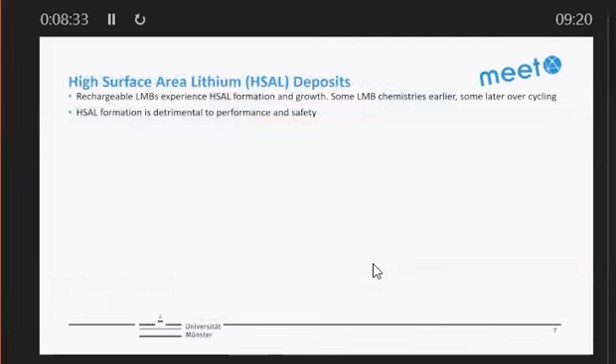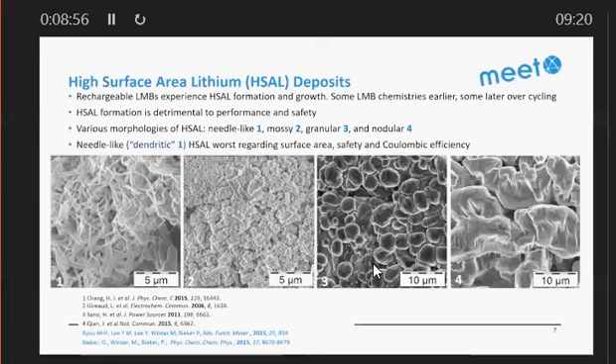Okay, high surface area lithium metal deposits, there are quite a few. And actually, all of the lithium metal batteries, including solid state, fail after some time because lithium metal gets deposited more roughly. Okay, it can be even hundreds of cycles, sometimes over thousands of cycles, but they fail because of this high surface area lithium deposits. And high surface area lithium formation is really detrimental for performance and safety. That is already proven.